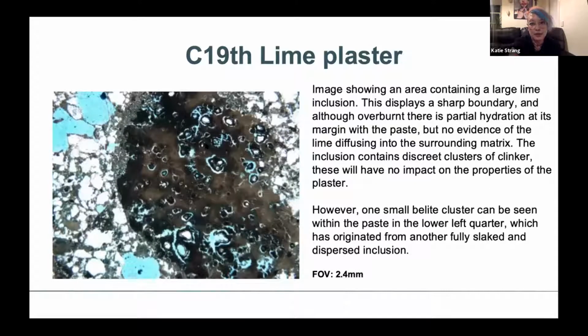But here's another lime inclusion, and as I said before, we were having issues with the pop outs on this plaster, so that's why we concentrated on looking at these lime inclusions, trying to find out what was going on. So there is a sharp margin on this one, and it has been overburnt, which is all the really, really dark areas there. The reason this happens is because the kilns were not controlled in the way that we would control them now. There were different hotspots within the kiln, so parts of the kiln could be burning at a way higher temperature than others, and that was just to do with how non-uniform they were back in the day and how they prepared those mortars.